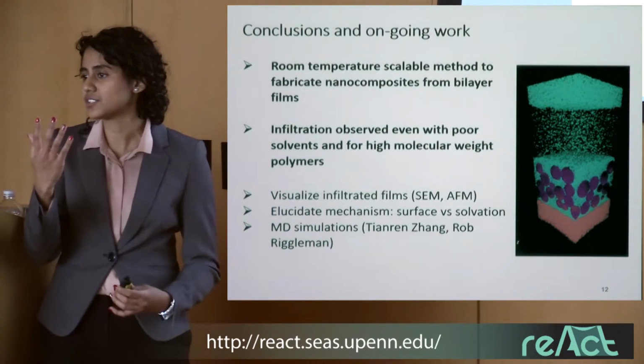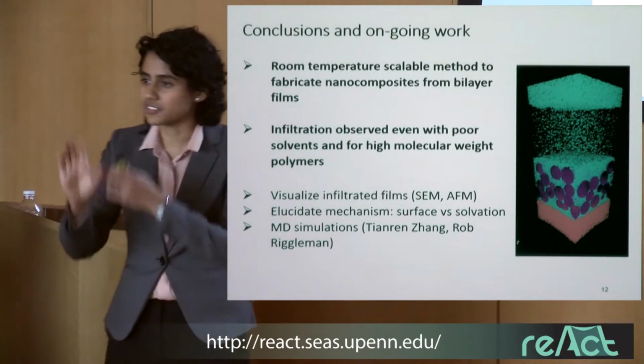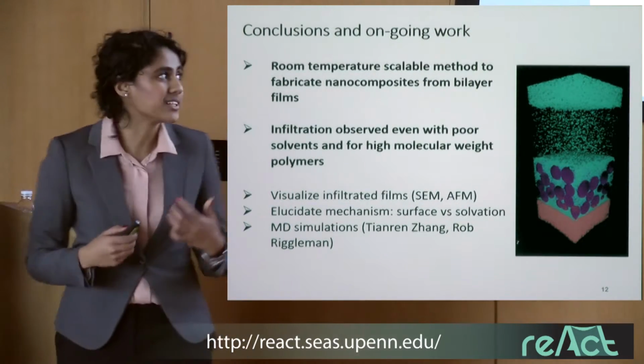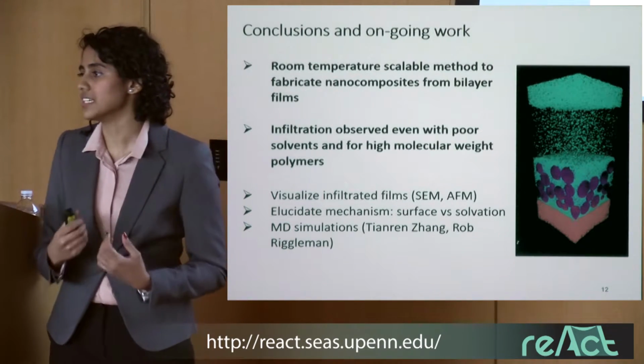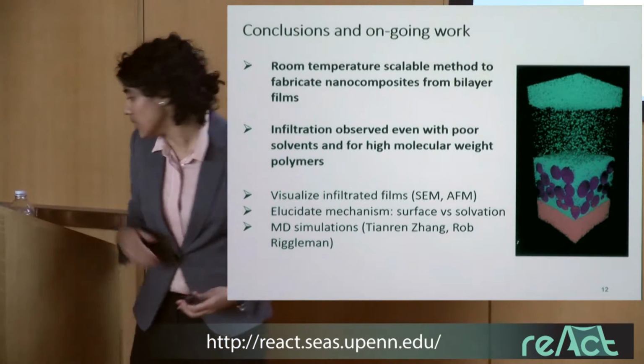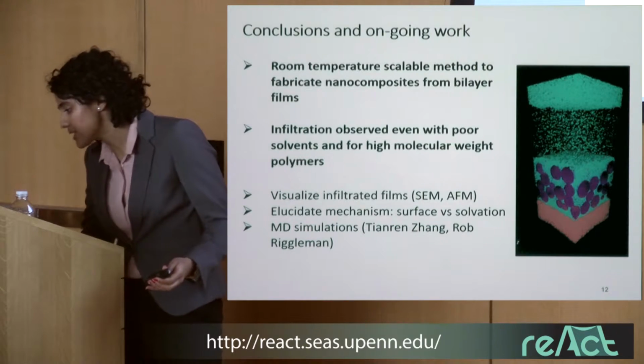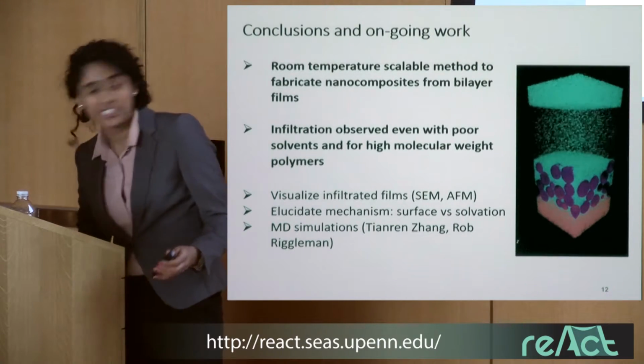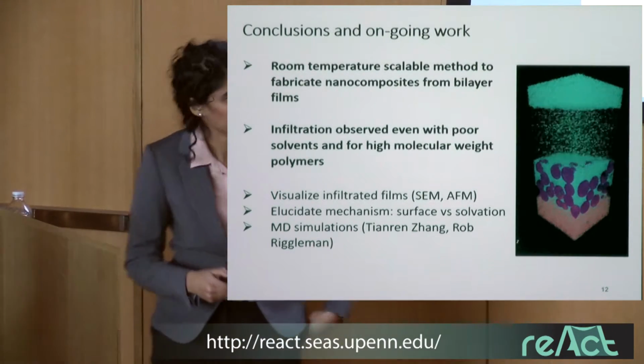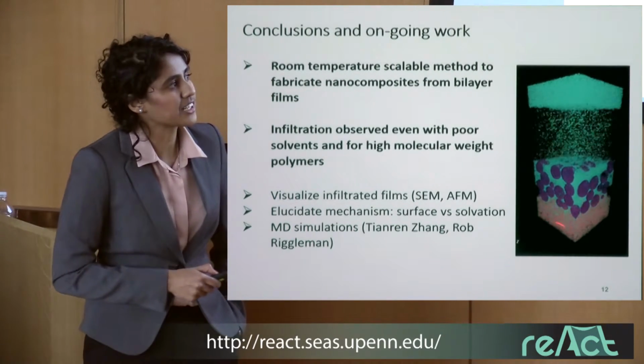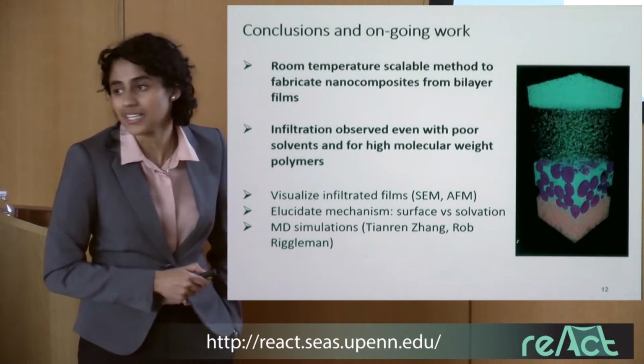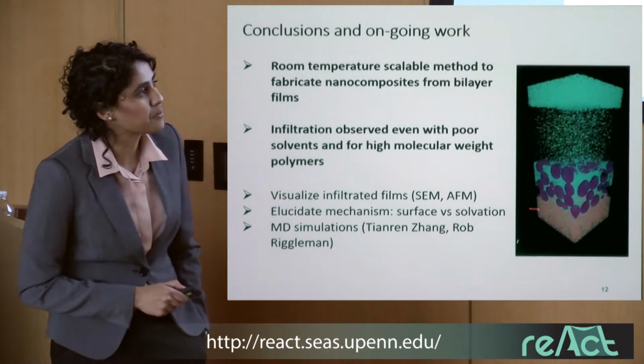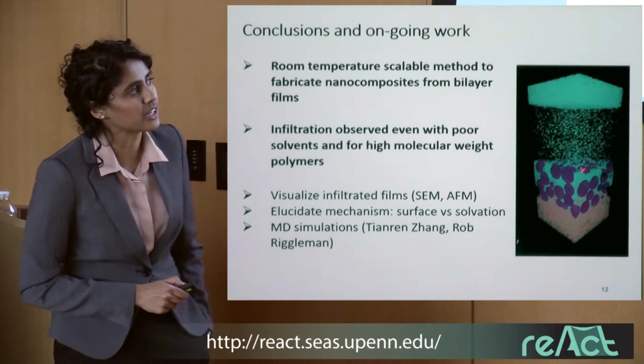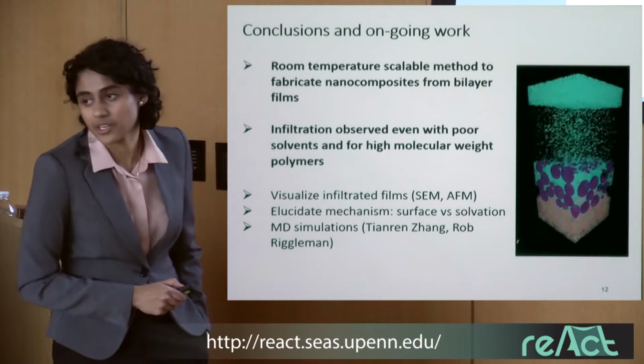One could be solvation-driven entirely, another could be surface-mediated. So we really want to understand what is driving the polymer to infiltrate in these systems. One thing that we're doing in collaboration with Dr. Riggleman is running simulation studies. And in this simulation, much like our experimental system, we observe swelling initially, and then we see that polymer slowly begins to infiltrate as a front into the nanoparticle packing.